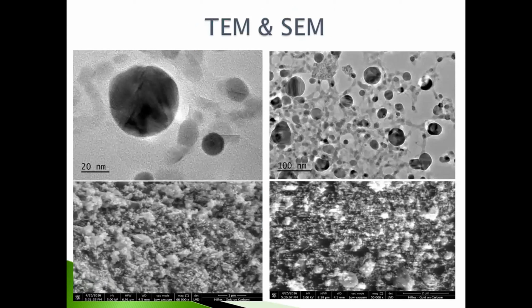Then also the imaging, TEM and SEM imaging was done, and we can see that nanoparticles were well dispersed and very much spherical in shape. Very few nanoparticles are of deformed shape. Most of them are very much homogeneous, and they are in spherical shape. Their size we can see as we compare it to the scale. We see that it is in the vicinity of 20-25 nanometers. Through the SEM data, we can confirm that as well.